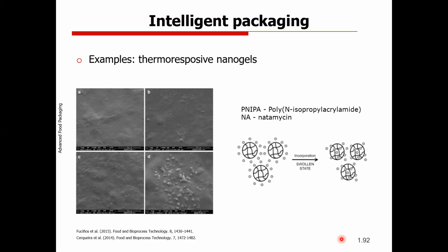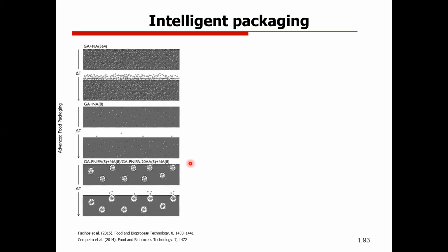In this case, we use these nano hydrogels based on this PNIPA, and we incorporate natamycin, which is a very well-known antifungal used in cheese and meat products. And we add these nano hydrogels to a polysaccharide-based film. You can see here some of these nano hydrogels on the surface in these scanning electron microscopy images. And we approach this in a simple way.